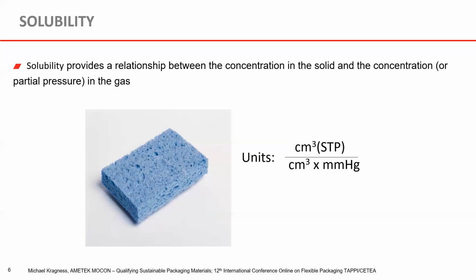Then we do this test again at 100% relative humidity. Now, the solubility factor, since it's at the same temperature and the same type of paper, you'll get double the solubility, or double the weight, at 100% relative humidity as you would at 50% relative humidity. That's because the solubility is heavily influenced by the concentration. One case is 50%, one case is 100%.